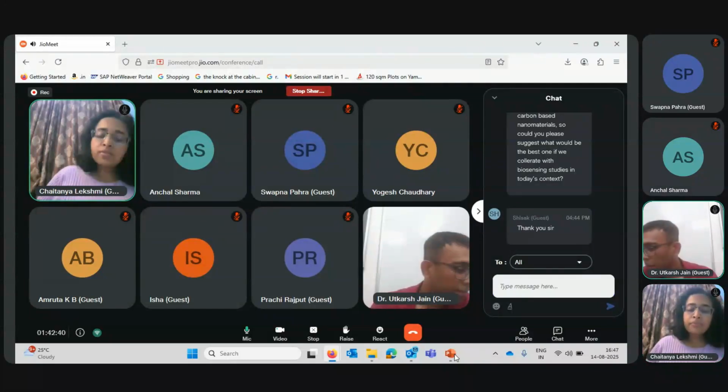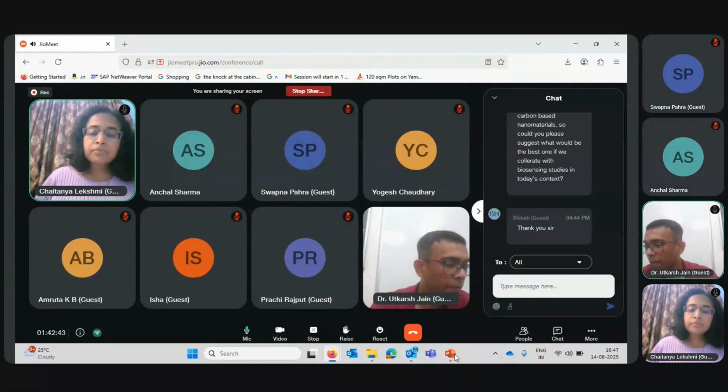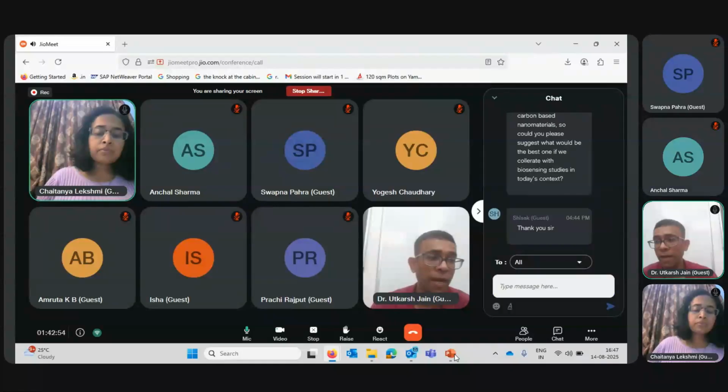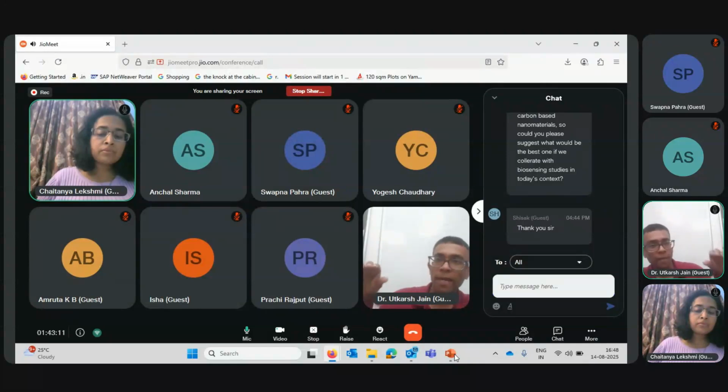Yeah. I cross-checked: previously we were only working on chronoamperometry, with enzyme-based biosensors. But I can tell you that when we started working on molecularly imprinted polymer, EIS gave really good data. It is actually on par with the enzyme-based biosensor where electrons were generated. But with molecularly imprinted polymer, the entrapment of the template molecule or a specific molecule in the polymer layer was really significant.